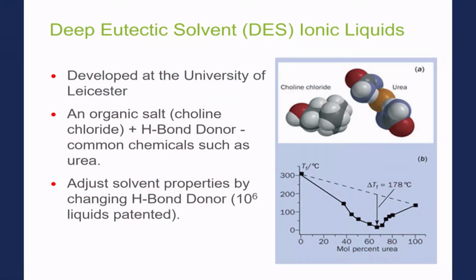And we mix the two together, and they may have high melting points themselves for the two things. This is the urea, but when you mix the two together, you form a eutectic mixture that is liquid at room temperature. So we have patented over 1 million combinations of possible liquids, and that allows us potentially to adjust the solvent and its properties for particular applications.